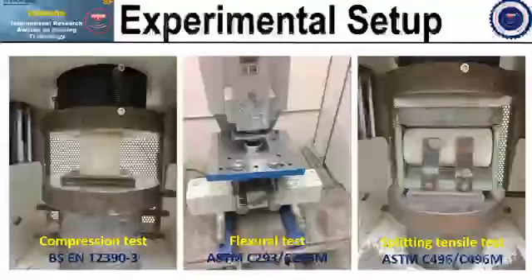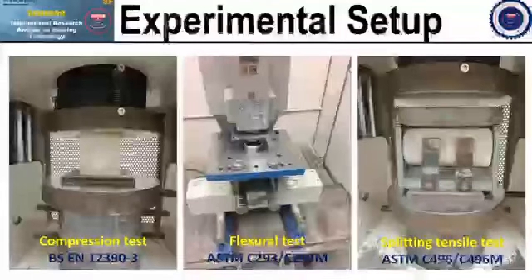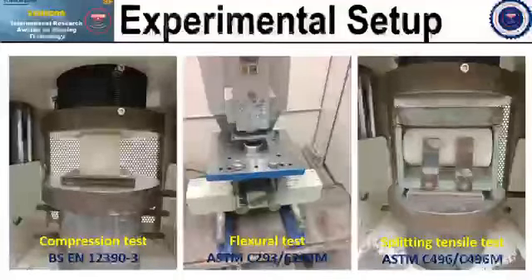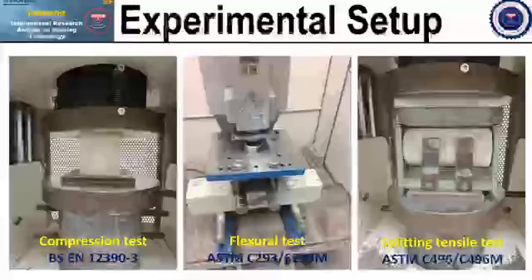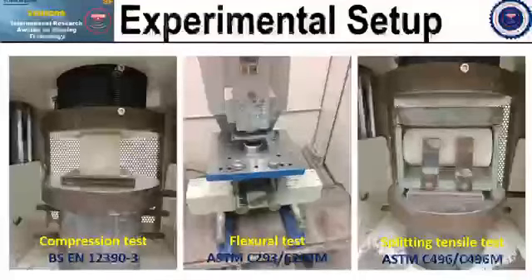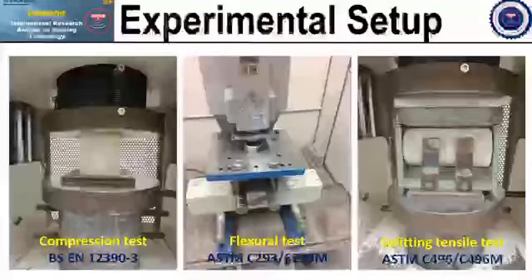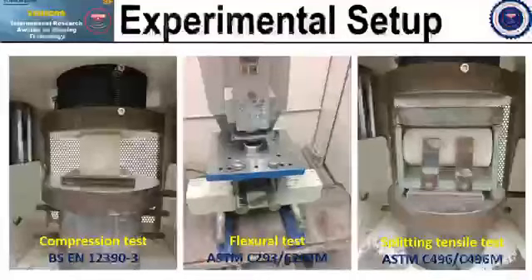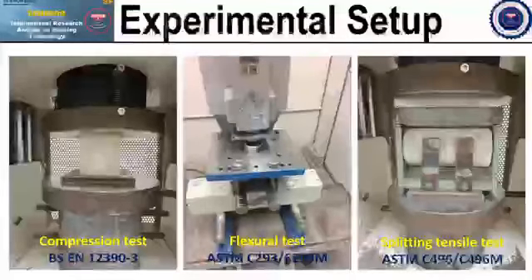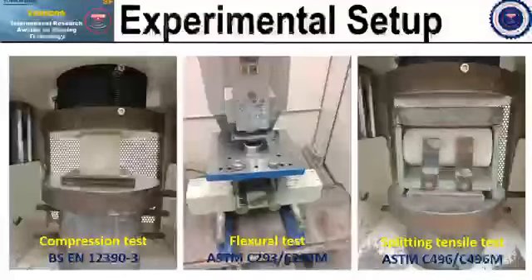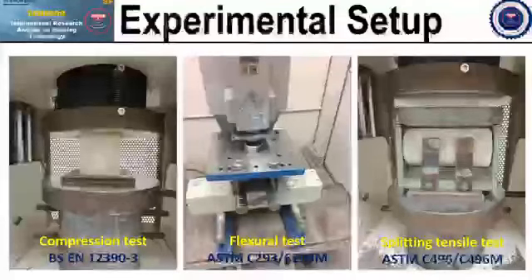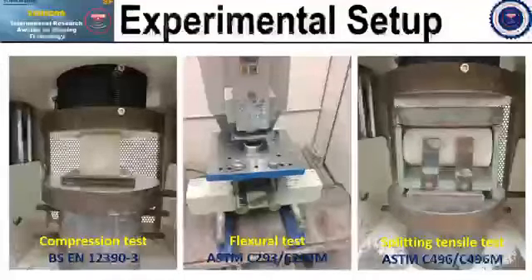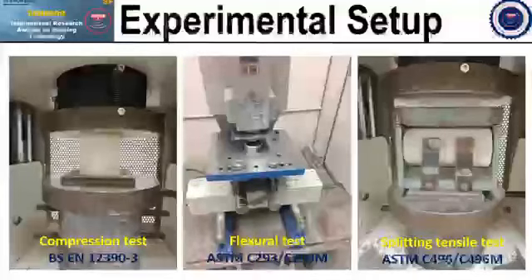For the flexural test, I use a prism of 100 times 100 times 500 mm, which is according to ASTM C293. I use a 3-point bending test to obtain the flexural strength of the lightweight foam concrete. Then for the splitting tensile strength, I use a cylinder with a diameter of 100 mm and a height of 200 mm, which is according to ASTM C496. That's a little bit about the experimental